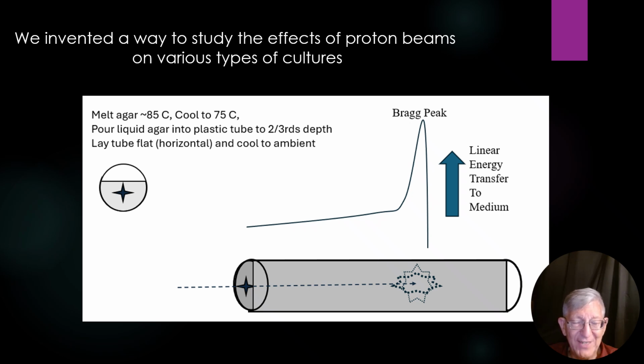And so we have invented a tube. We basically take a plastic tube about 10 centimeters, 12 centimeters long, and fill it 2/3 of the way full of liquid agar. Then we lay it on its side and let it cool in a refrigerator, and we end up with a very nice cross section, very much like the circle on the left here. And then when we fire our proton beam down through here, it goes a certain distance, as shown by the graphic here. The graph shows where the linear energy transfer is and where the Bragg peak occurs.